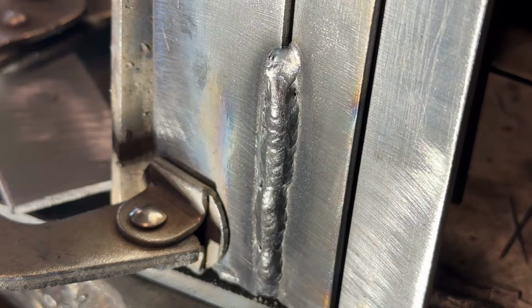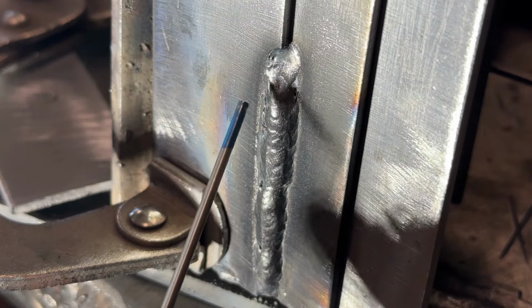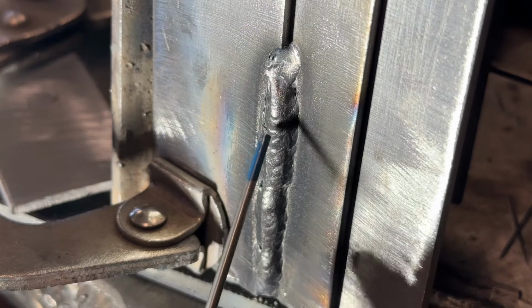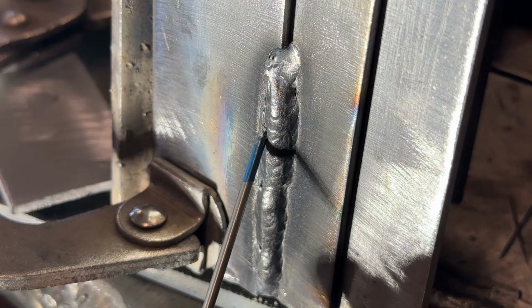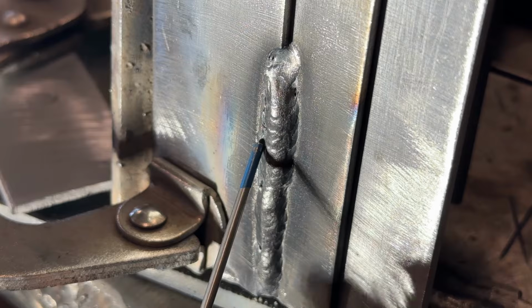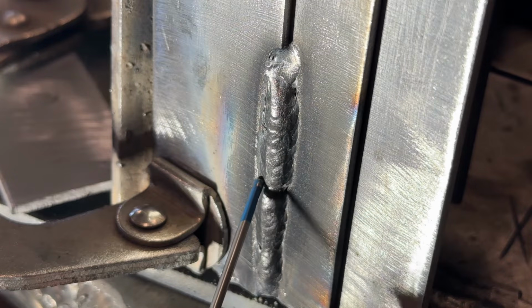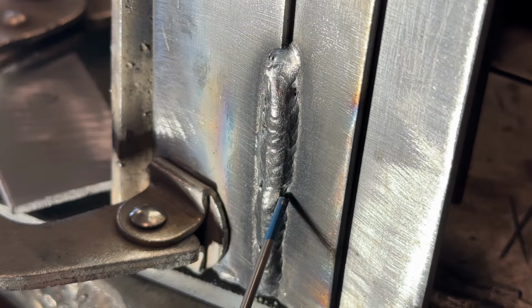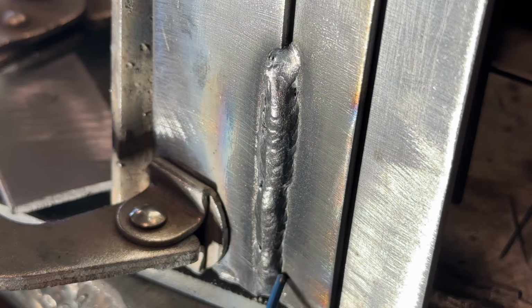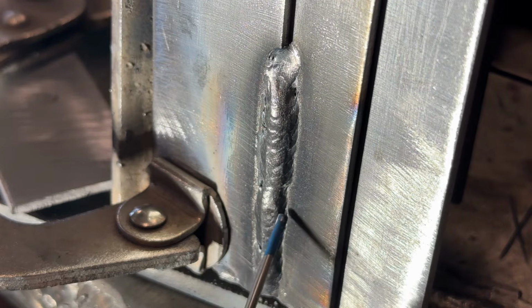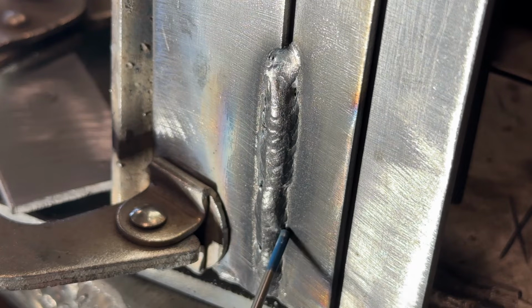So let's talk about what we see here. Now, I was able to successfully weld vertical up without having it drip, but there's room for improvement. So we've successfully made it. The bead looks a little bit tall, so it's a little bit far off the plate. There's evidence of a little bit of pin dot porosity, and if you look, this appears to be not crowned up like caulk, but it looks like it could flow out a little bit more.